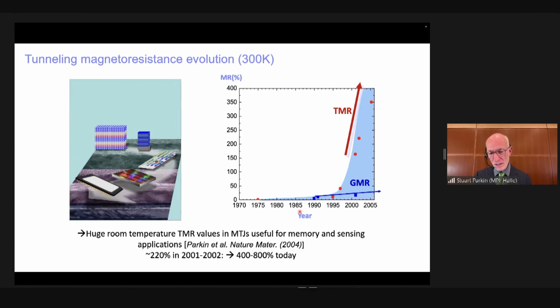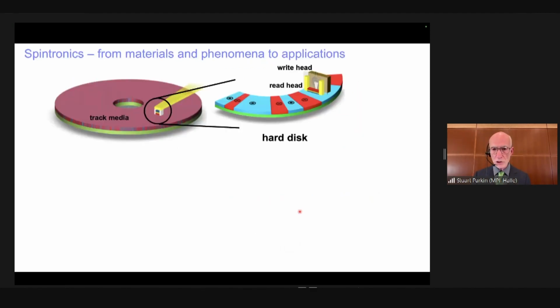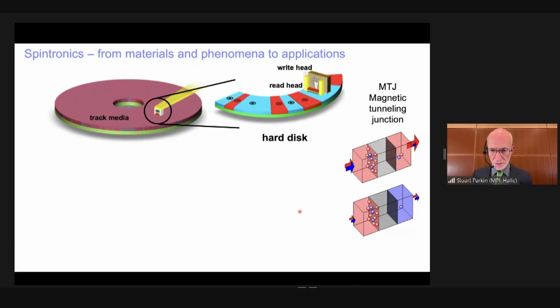And this was by using a combination of a magnesium oxide tunnel barrier connected to a particular magnetic layer that has a particular configuration, a body-centered cubic configuration, in which the electrons extracted from the magnetic surface are spin filtered through the tunneling barrier to enable extremely high spin polarizations of the current. And we've achieved spin polarizations of more than 95%. This enables these huge changes in tunneling magnetoresistance. So then what happens? We could use this tunneling junction principle in a spin valve configuration to read information in a magnetic disk drive. And these tunnel junction spin valve devices have been used since 2007 in magnetic disk drives.